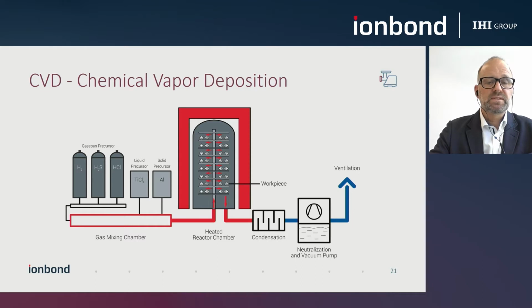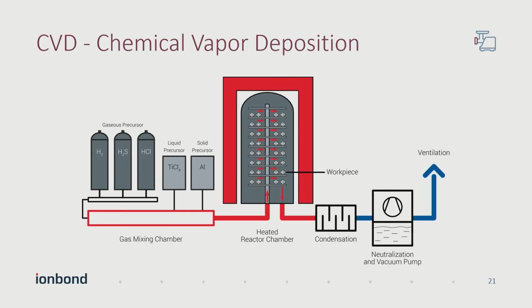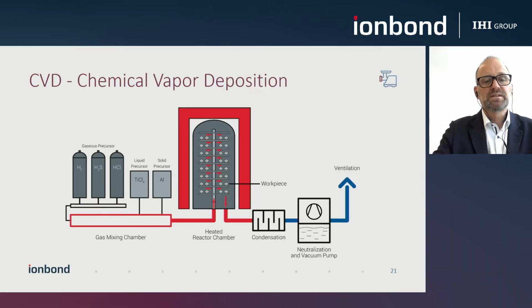We have different precursors. We have gaseous precursors, we have liquid precursors, and we have solid precursors. The gaseous precursors here, for example, the hydrogen or the hydrogen chloride, we can add straight because they're already gases. Liquid precursors and solid precursors need to be evaporated prior to filling them into the retort. The retort or the reactor itself, this is the gray dome we see in the middle of the picture. This is made out of steel, and a heating cap is placed over this dome, which will heat up the reactor. We fill in the vapors, and the chemical reaction is taking place, creating the coating on the parts.